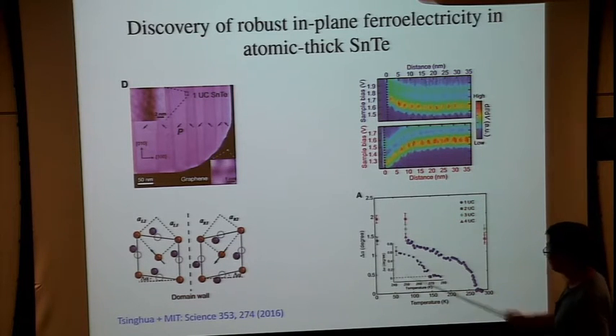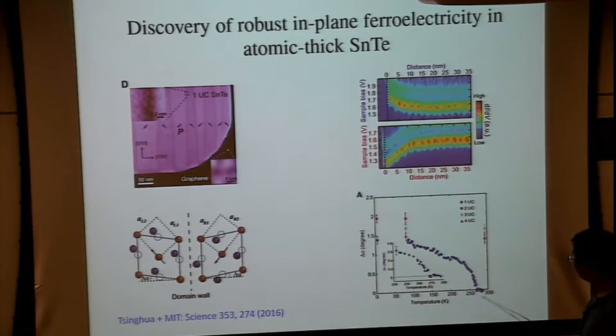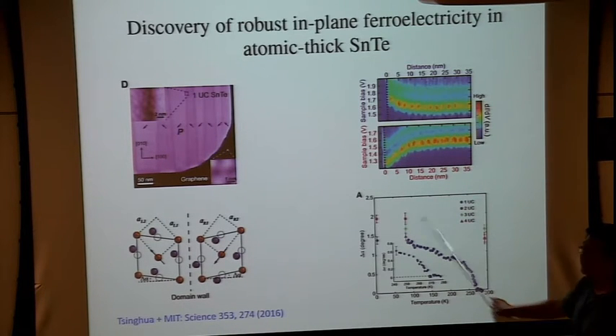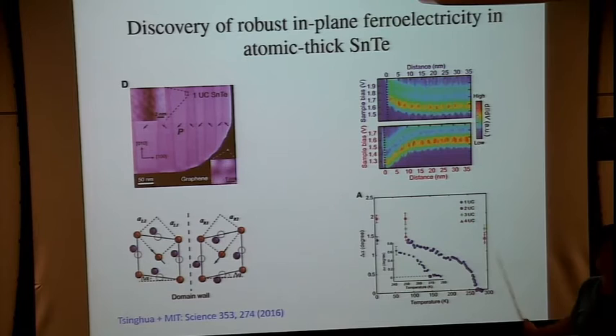Now, looking at this distortion as a function of temperature, we found that the distortion actually goes to very, very high temperature. In one unit cell, 2 atomic layer thin tin telluride, the distortion onsets slightly below room temperature. But for 2 or 3 unit cell thick samples, the distortion is present even at room temperature. Presumably even at much higher temperature it is still present.